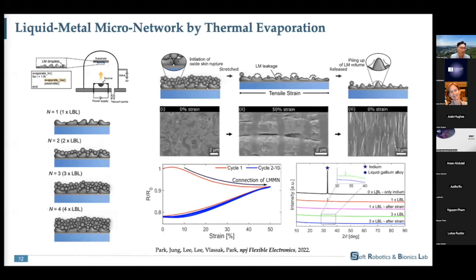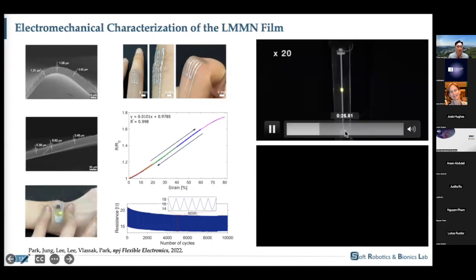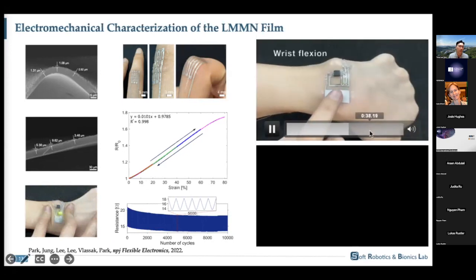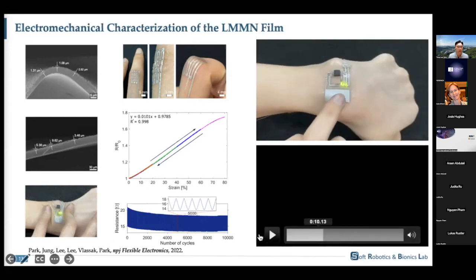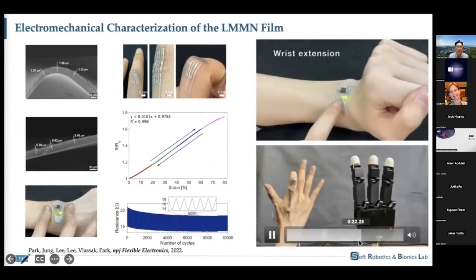As you can see in the figures in the plot, the first stretch makes the connection, but after that, you have a really nice response of the resistance. And you can build very, very thin sensors using this method. As you can see here, we were able to deposit a liquid metal layer as thin as 1 micron, and also the layer was about just 5 micron or 10 micron. So in the video, we can see this is highly robust, and we can build a skin mountable device. And also we can use this sensor as a teleoperation system.